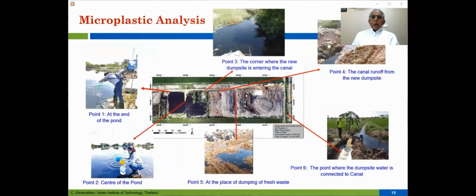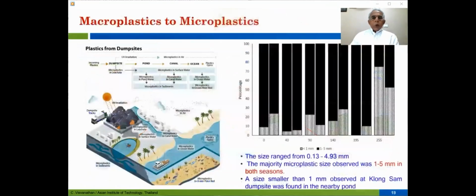Next, we looked at micro analysis. We collected the leachate from different locations, and we did the micro analysis in terms of plastic. And this is quite interesting. Here you can see incoming waste takes you to the dump site. Then we have the ponds, and from here some of the plastic, using the UV radiation, breaks down, some of these macroplastics become microplastics, and eventually they start moving along the line to the aquatic environment and eventually lead to the river.